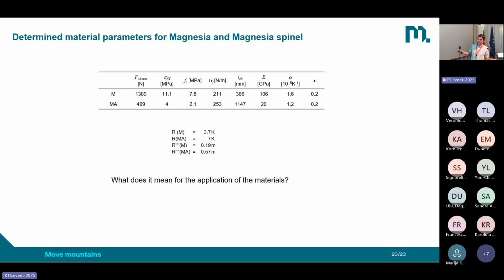For the magnesia spinel, we have a much lower strength, 2.1. 2.1 megapascal is not much. We have a little bit higher specific fracture energy, but I would say not significantly higher, but a much higher characteristic length. What does it mean now? If we calculate R, the Kingery parameter, and the Hasselmann parameter, we see here for Kingery, for this parameter set, for magnesia, we need only a temperature difference of 3.7 Kelvin to have crack initiation in our refractory product. And if you think now about the applications we have and the temperature differences in the linings, in the refractories, you may have an idea that we cannot stay below 3.7 Kelvin. So this is somehow absolutely impossible. So in any case, we will have crack initiation.